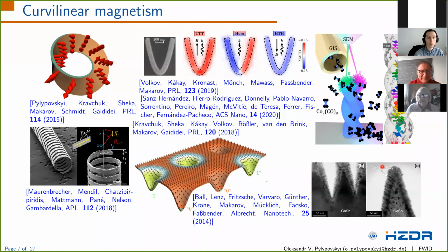Nowadays, by curvilinear magnetism at all, one understands the investigation of the interplay between the geometry and magnetic textures. It is well developed for ferromagnets. Let us imagine a curvilinear ferromagnetic wire or thin shell. In this case, the magnetostatics induces a specific shape anisotropy, which tracks the geometry. Also, ultra-thin films grown on an inhomogeneous substrate or shaped via strain engineering possess the easy axis of the anisotropy, which is normal to the shell surface. These shape or easy normal anisotropies allow the magnetic textures to know in what geometry they live and possess some geometry-driven features.